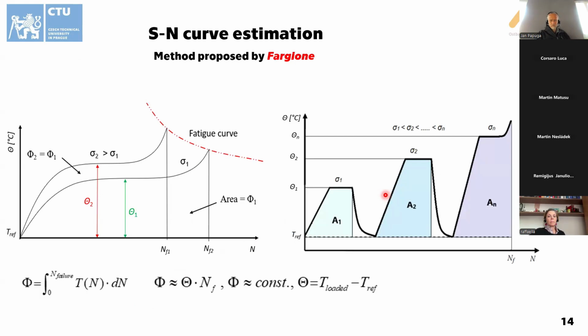What we were trying to use was Fargione's method. Fargione, I think around 2001, postulated that there is something called the limiting energy that can be calculated as the area under the temperature evolution from the start of the test until the failure of the specimen. This concept of limiting energy is supposed to be a constant value for a variable amplitude of load. This is schematic as I think it should look, and he also postulates that when the summation of the area under the step test is done, this should be equal to the limiting energy from the single level test. So this is the single level test and this is the self-heating step test.